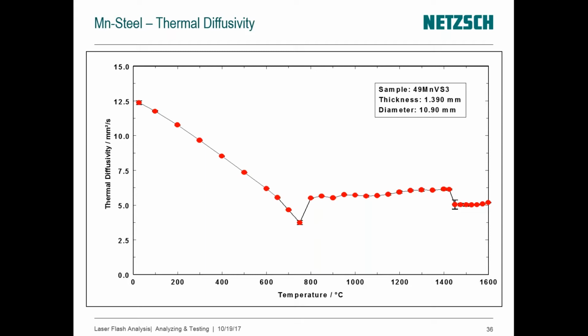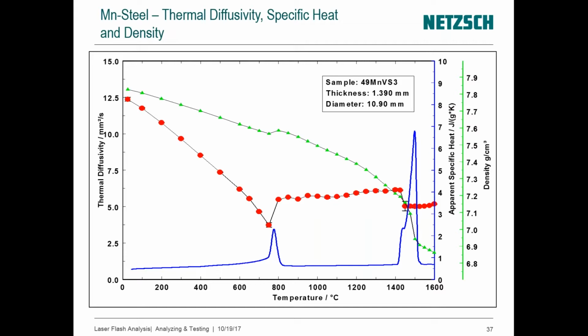If we were to combine all this information with what would be obtained with a DSC, for example, then we can see whenever the phase change occurred. That is represented here with the blue curve, where we see the energetic events. The first peak of the DSC signal would be due to the phase change, and the second peak will be due to the melting of the specimen.